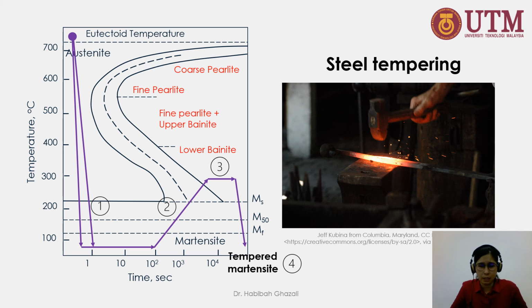But the problem with this process is that the outer layer, or the outer structure of the metal, the steel, will be transformed to martensite first, followed by the inside structure of the metal. So this will generate stresses and strain during this quenching process. So they came up with another heat treatment procedure that they call Martempering that will eliminate this effect.